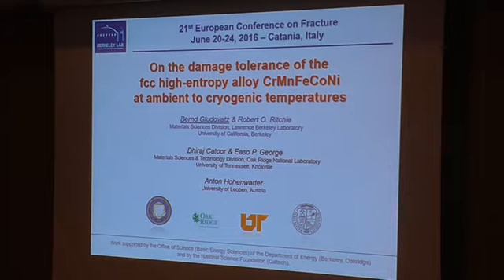We also see a lot of such recrystallization twins and maybe a few such nanoscale deformation twins, even though they were extremely hard to find at room temperature, so that we think we can clearly say that at room temperature, like in the case of the tensile strength, the deformation is mainly carried by planar dislocation slip and by dislocation motion.